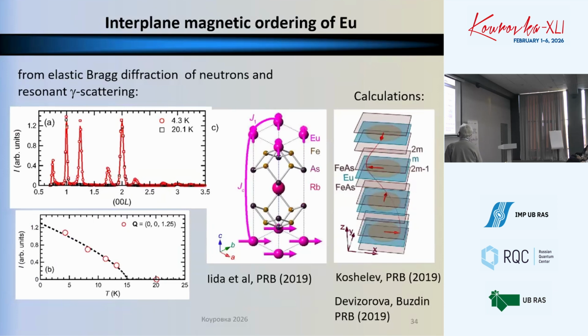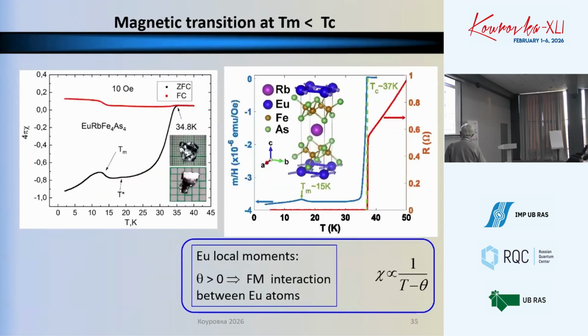Here, from resonant gamma scattering and elastic Bragg diffraction, it was found that the step size in the helicoid structure is pi/2. It's interesting. Nevertheless, it doesn't change the physics. When we study resistivity, it shows a nice superconducting transition at 37 Kelvin. This is a high temperature superconductor. And inside, in the magnetic response, there is a tiny kink due to Néel ordering. It can also be found in spin susceptibility measurement. You can analyze this and find that it has a ferromagnetic sign because the ferromagnetic ordering is stronger.